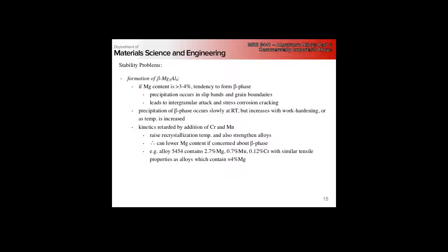And I talked about how the Navy is very keen on trying to find a way around this grain boundary sensitization problem, because they use these alloys for a lot of different applications in marine environments. You've got the perfect recipe for corrosion, and then extended times in tropical locations, you have ambient temperatures hot enough that you get grain boundary sensitization over the extended service life.